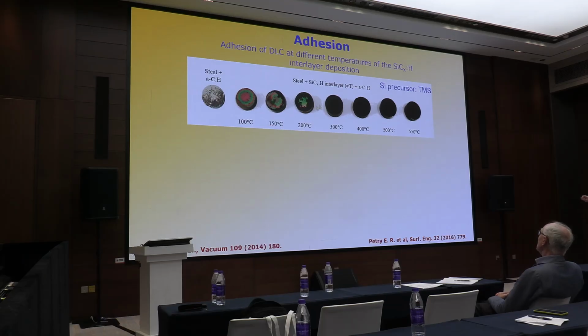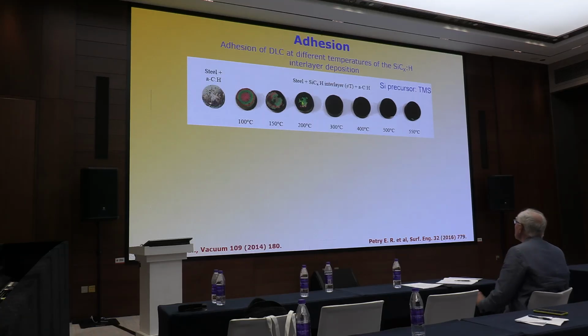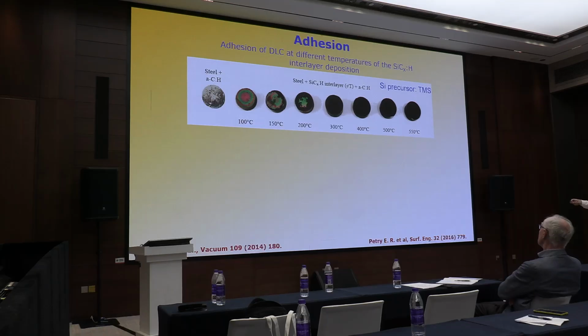This is a steel, and this is a steel with amorphous carbon or amorphous hydrogenated carbon. Here you can see the thin film, but here it is removed, delaminated. Here delaminated. The samples were prepared at different temperatures, different temperatures of the interlayer. Here we have steel and amorphous hydrogenated carbon. Here we have steel, an interlayer of silicon carbide, and then the hydrogenated amorphous carbon. When we modify the deposition temperature of this silicon carbide interlayer, we can increase the adhesion.